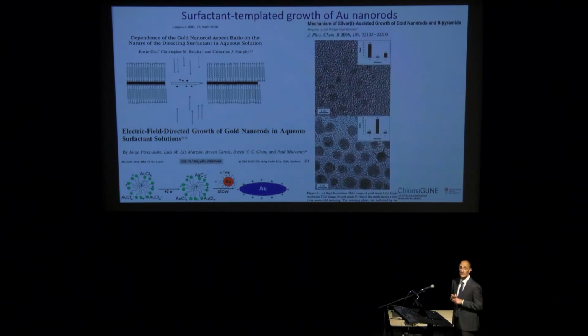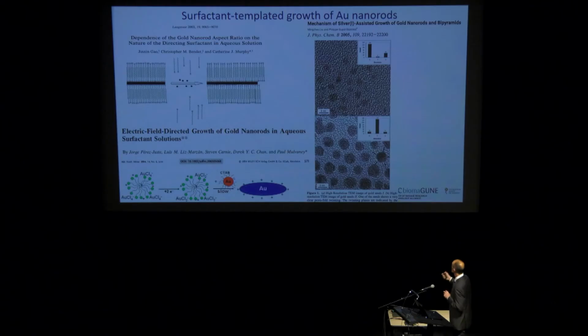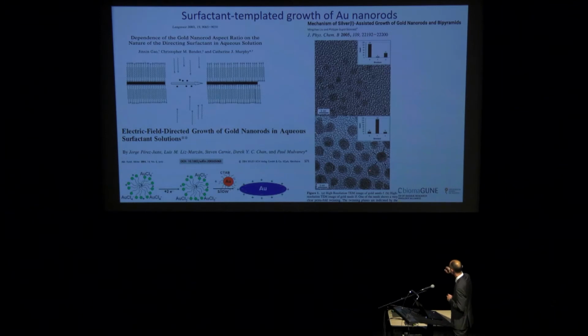But one of the crucial contributions came from Philippe Guyot-Sionest in Chicago, where he actually discovered that the two typical types of seeds that were used to make nanorods, either using sodium citrate or using cetyl trimethylammonium bromide in the initial reduction with borohydride, do not have the same crystalline structure. So they are, all of them, FCC, but the CTAB reduced or protected particles are single crystalline, while the ones which are reduced in the presence of citrate actually are pentatwinned. And this is what I signal here with these lines. If I would blow it up, you would see twin planes that create defects in these particles.